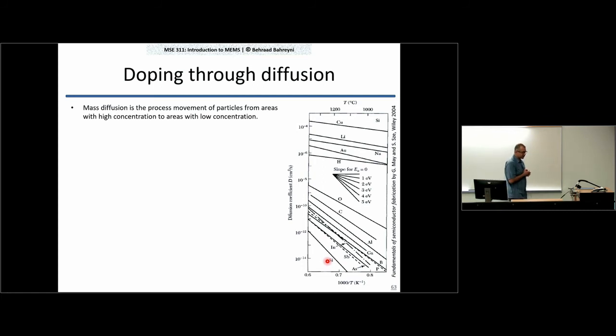Now, the challenge is that if you bring a lot of phosphorus and just expose it to silicon, they do not really go into silicon, right? So the diffusion of phosphorus, if you just keep it above silicon here, is really, really slow. It's negligible. You really cannot get any phosphorus into silicon no matter how long you wait. What we'll do is that we raise the temperature, we increase the energy in the environment, we make the phosphorus atoms more energetic, and by raising the temperature, we make it easier for phosphorus to diffuse into silicon.